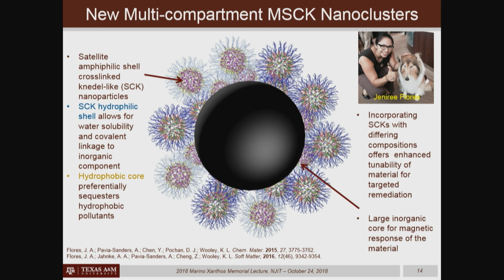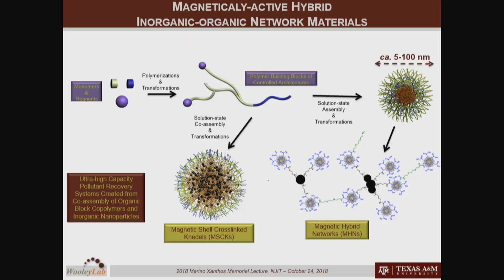Well, this was actually partly my design, and the failure of it, as I'll show you in just a moment, was partly due to the fact that we didn't understand that as nanoparticles get larger, the inorganic nanoparticles become permanent magnets. So when Jenny started this project, she was working with large inorganic iron oxide nanoparticles, and she found that they just kept clumping together because they were basically permanent magnets. And so she scaled back on the size of those particles, and she assembled this shell cross-linked Knedel-like nanoparticle without any iron oxide, and then was interested in coupling this organic particle onto the little small inorganic particles.